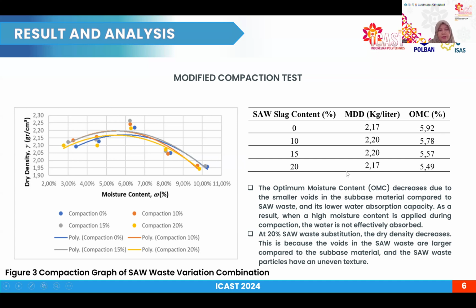At 20% SAW slag substitution, the dry density decreases. This is because the voids in the SAW slag are larger compared to the sub-base material, and the SAW slag particles have an uneven texture.